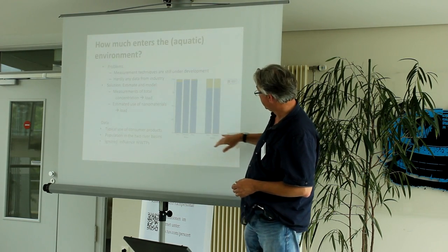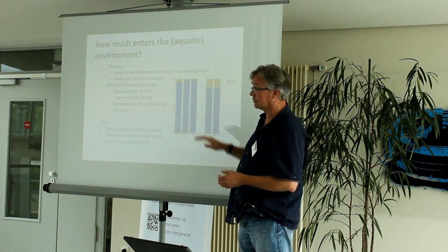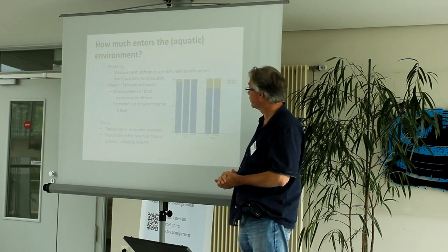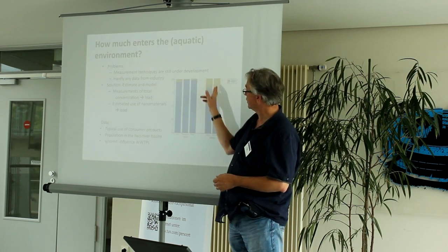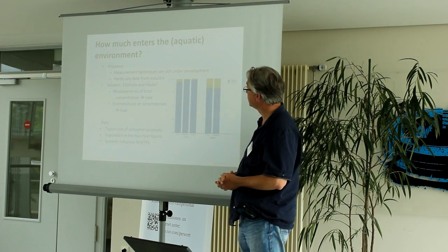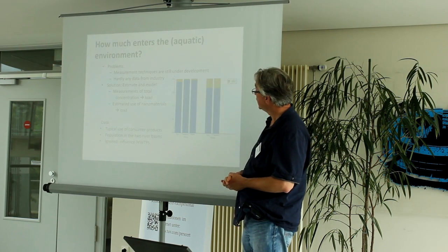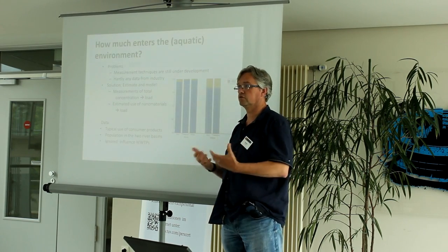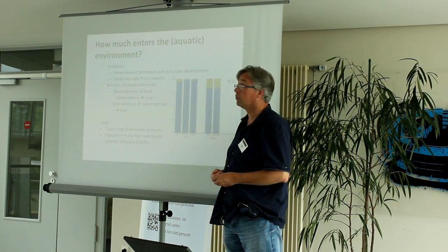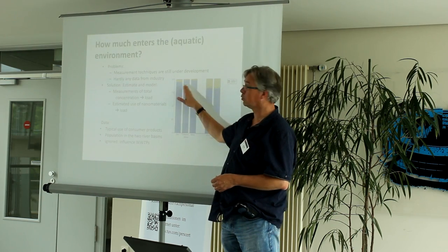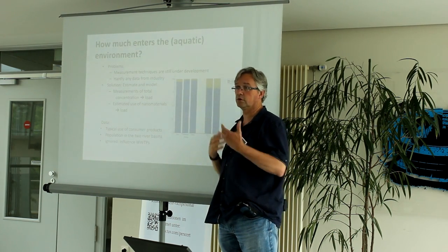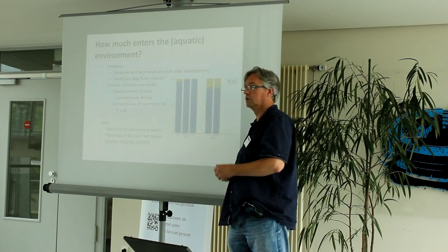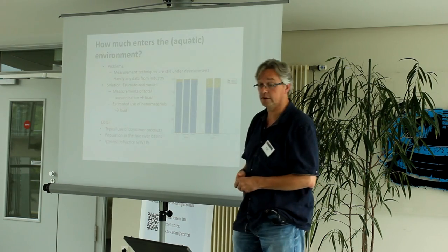So the blue one is what's coming in at the border. I'm afraid that's the border between the Netherlands and Germany. And this is what we, as Dutch, could add to that. And what you see is that even though these nanoparticles are said to be used more and more, they still have only a small contribution to the total contamination by zinc, titanium and silver. So that was the first result I obtained.